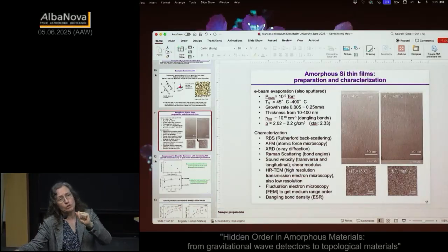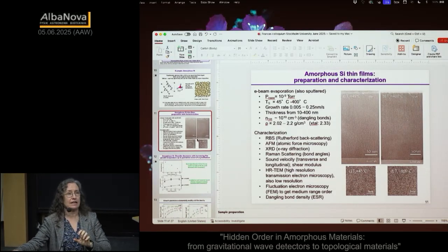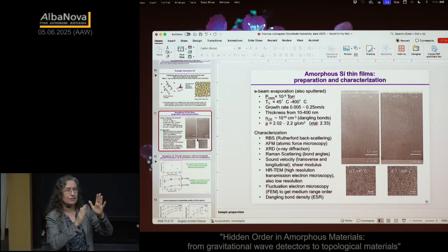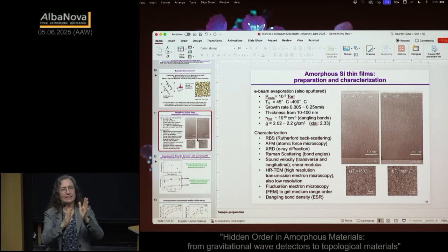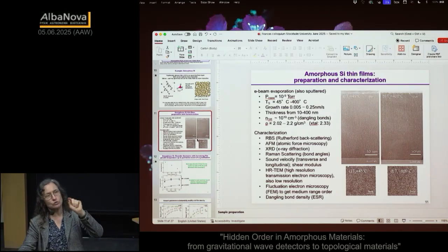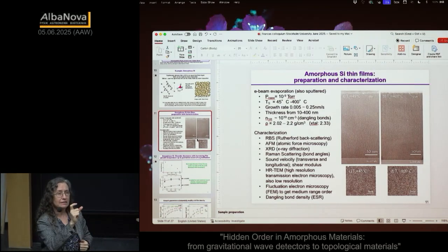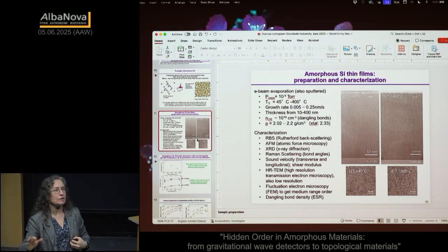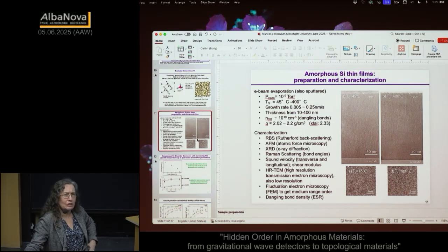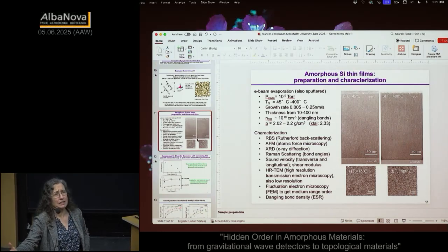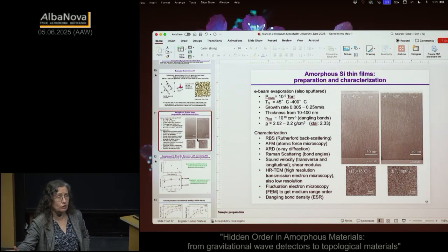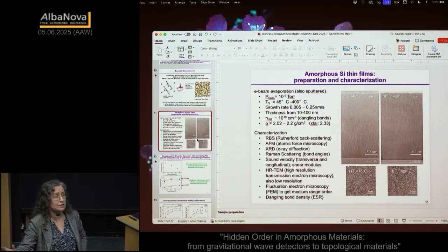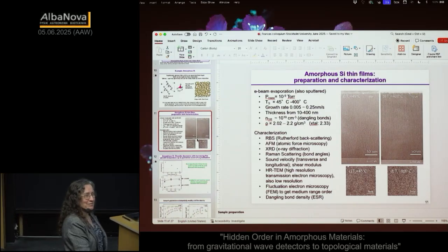So what we look for is we take high resolution TEM, which shows in particular no lattice fringes. Lattice fringes show up pretty early, and it shows what you're asking: you see a relatively sharp ring, but no spots. And so, yeah, I guess I haven't. I think the sharpness of the ring maybe could be used. Yeah, that's an interesting question. I don't know that we've ever. I mean, you could ask the same thing about liquids. In fact, it probably is the same problem in liquids. Liquids also don't have long-range order, and also are not nanocrystalline or quasi-crystalline.